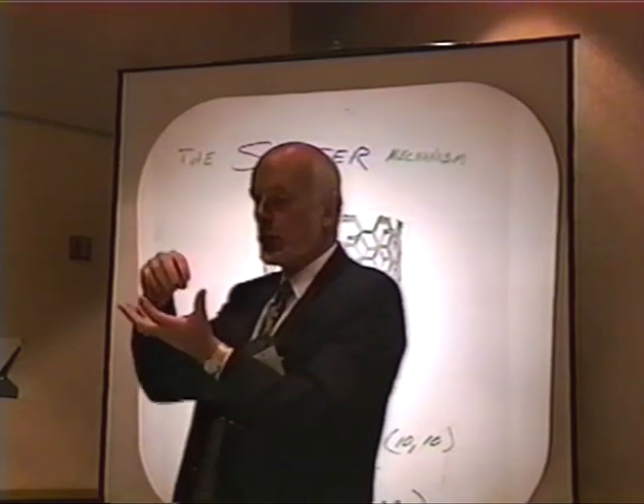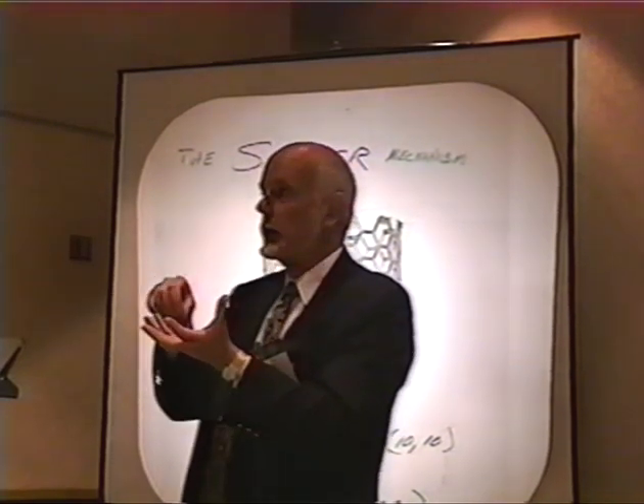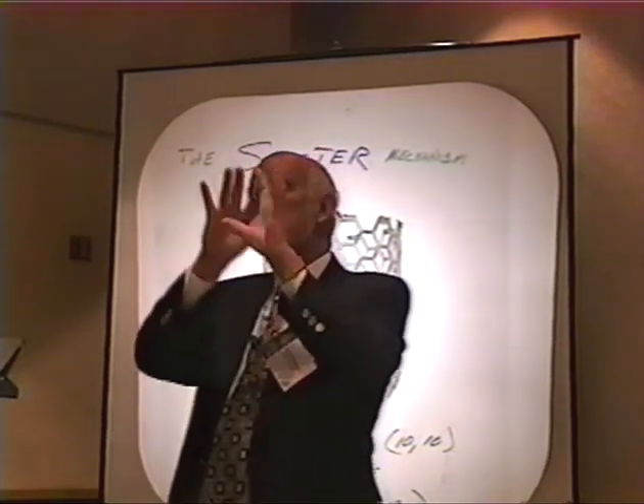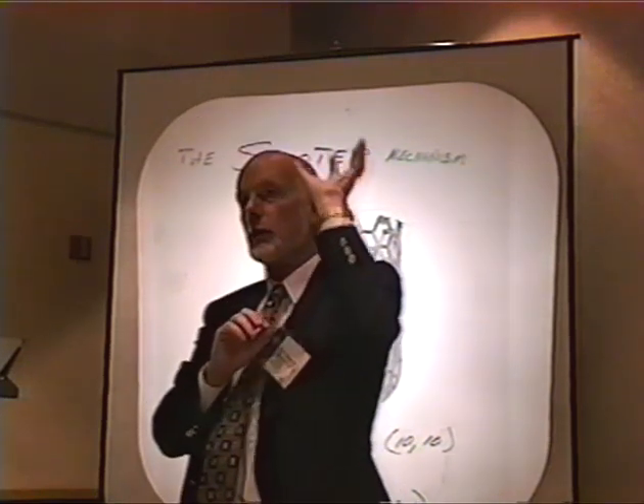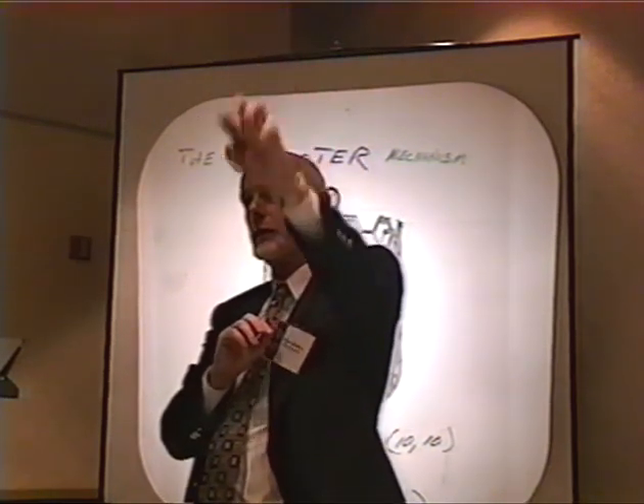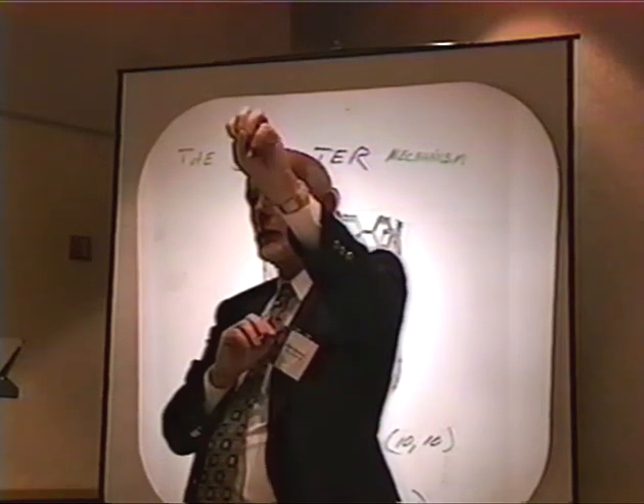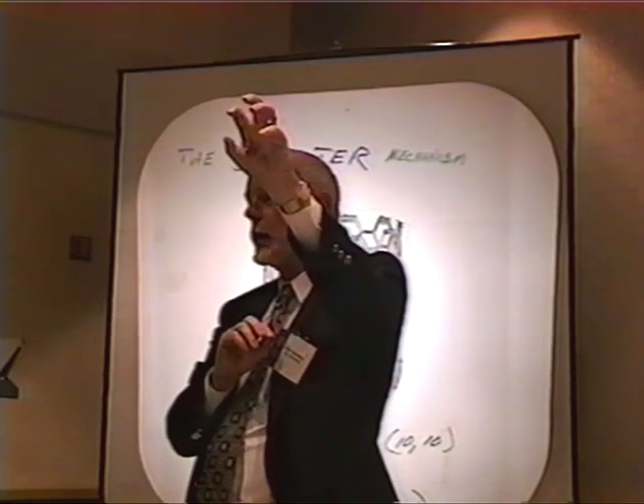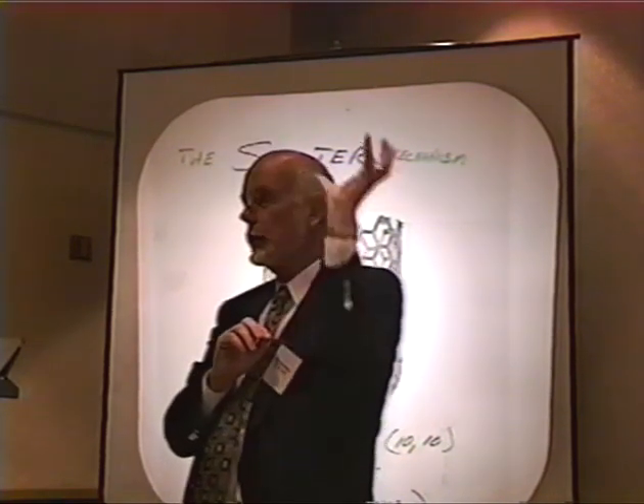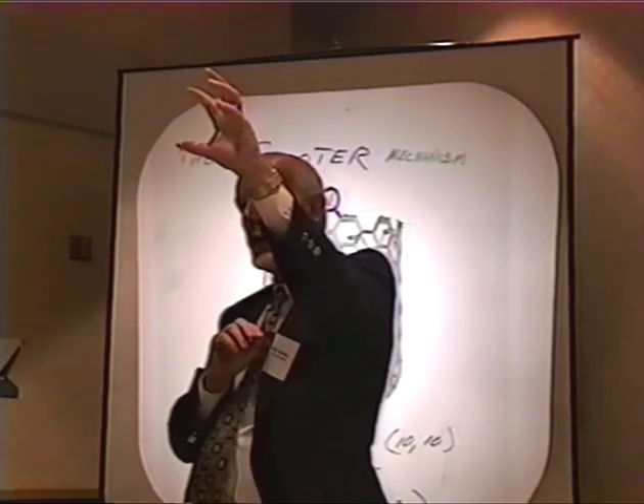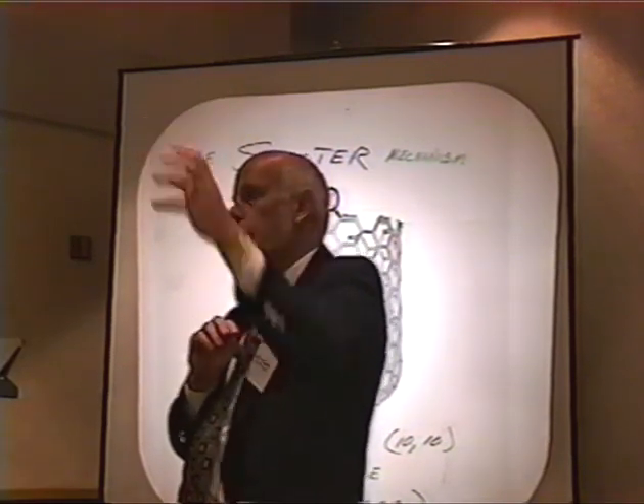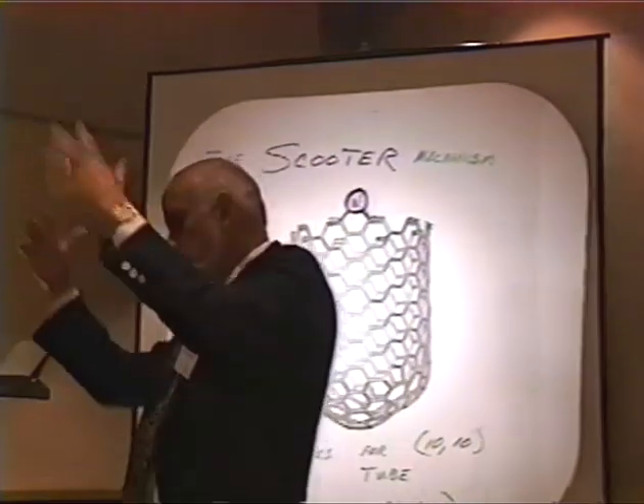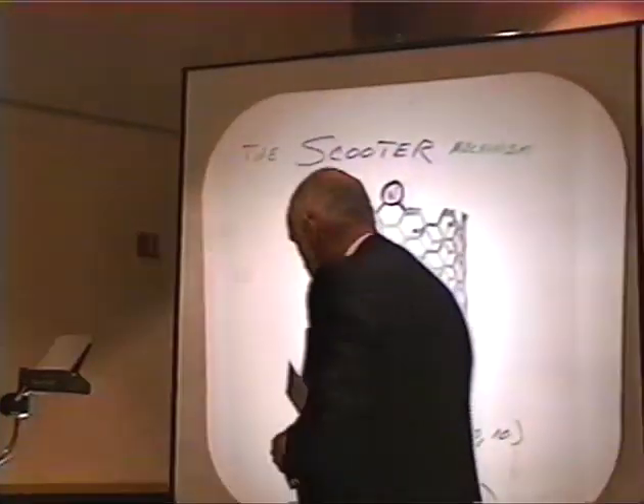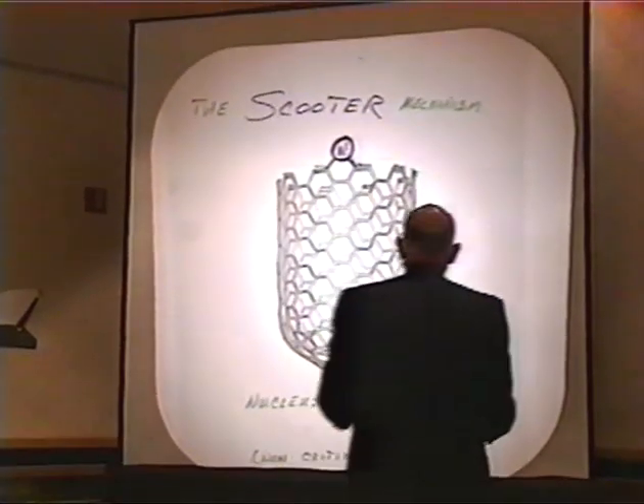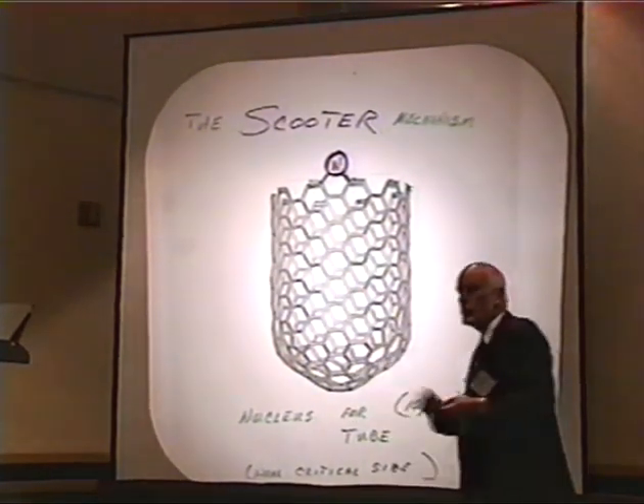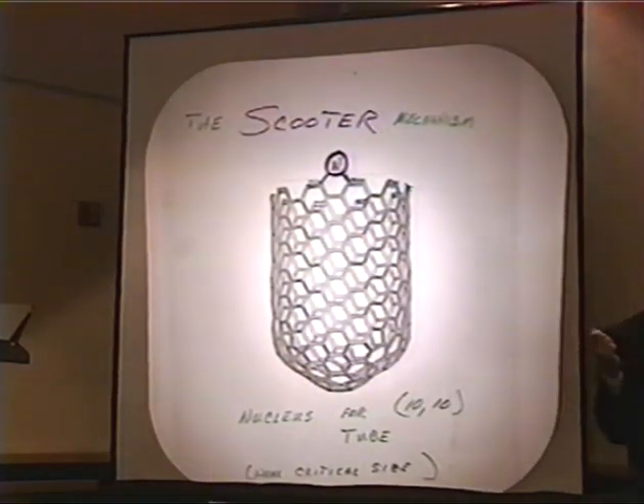Well, it turns out that the pattern of pentagons that does that and maintains it as you curve around is precisely the pattern of pentagons that will give you C60. And that's the reason we think that C60 forms in such high yield, is that kinetically there is a path, which is the lowest energy path that goes there. If you don't quite do it perfectly, you'll make some other full ring before it closes off. Well, we think that these tubes are basically a detour off of that path.